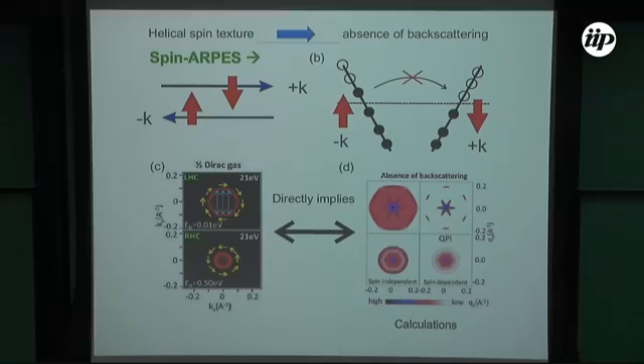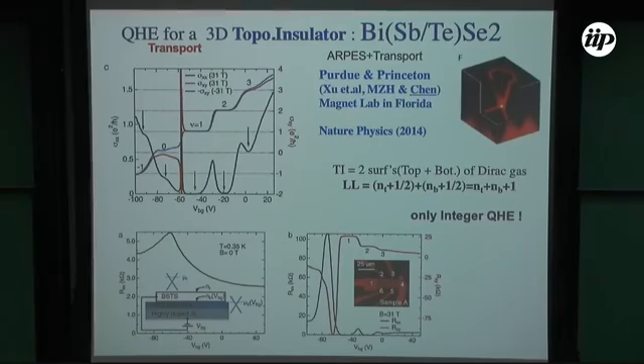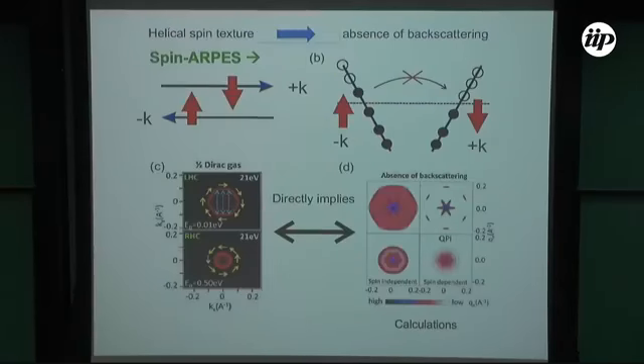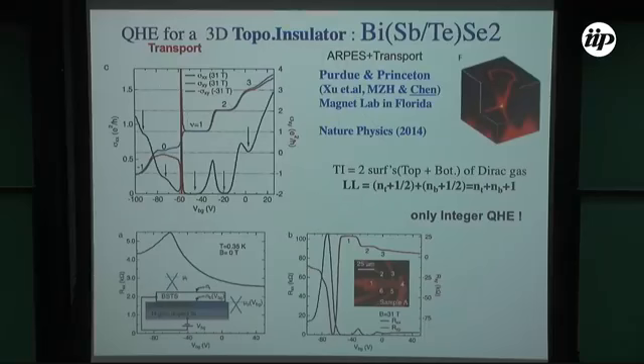So this absence of backscattering, you can also see in STM, and then you can map from the ARPES Fermi surface to the STM quasi-particle interference pattern. Okay, so then how do we know that these states exist outside the vacuum? All these experiments I showed were performed under ultra-high vacuum, and the surface is prepared in a special way. So one way to check that you have surface states is to do transport.